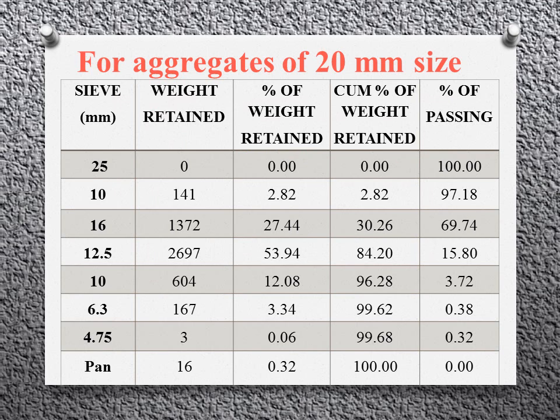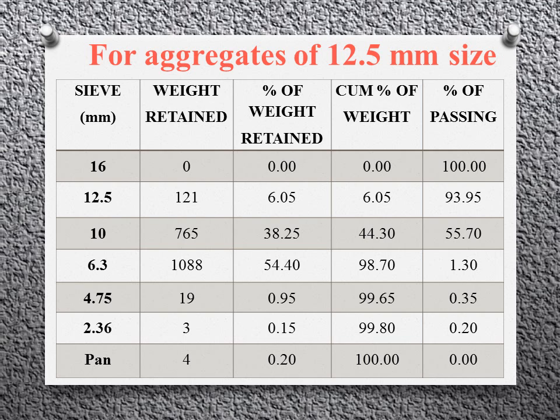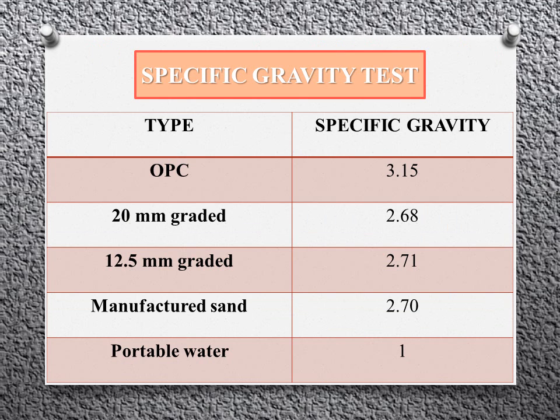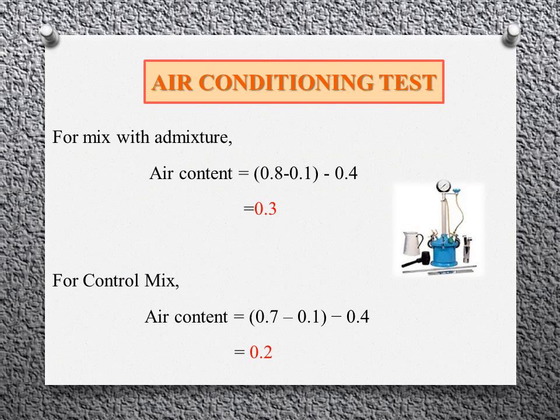Sieve analysis was carried out. The sieve analysis for aggregates of 20 mm size and 12.5 mm size is shown in the tabulation. The specific gravity test was carried out, and the materials used and their specific gravity values are shown. The air content test, which was carried out to find out the air content in the concrete mix, was done for both the control mix and mix with admixture, and its values are shown.